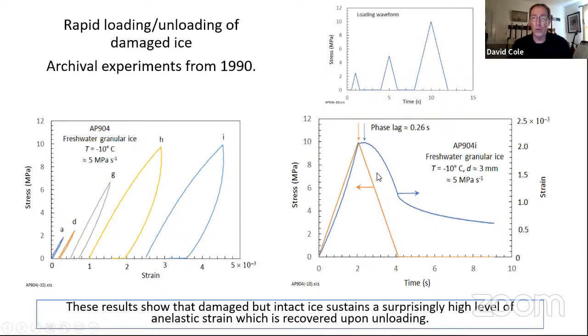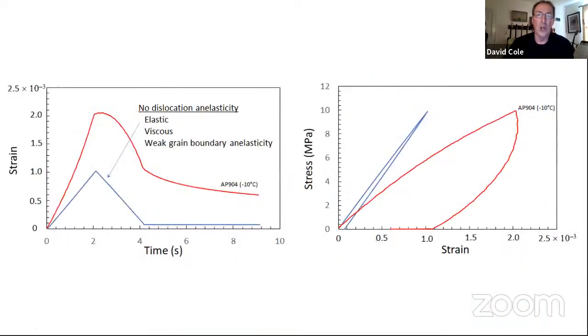And so what I'd show you now is we're confronted with trying to model this behavior, which, spoiler alert, is in fact due to dislocation anelasticity, but let's build up to that point. If the red curve here is the actual response from our specimen, nothing theoretical about this, it's actually observed. I don't have an awful lot of experiments, but enough that it's a reproducible phenomenon when the ice can sustain this amount of damage.